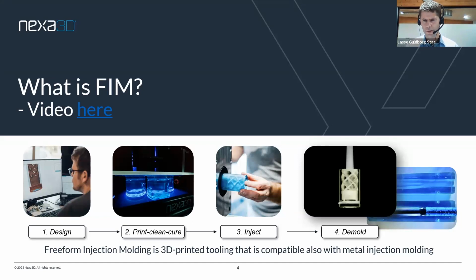Step number 3 is the injection of material into the printed mold. We use standard injection mold machines. We use standard injection moldable materials like the xMOLD feedstocks that Sebastian is going to talk about a little later. And then as the 4th step, we provide the injection molder with 2 alternative demolding patterns. For simple parts and for non-stick materials, we offer the opportunity of simply splitting tools apart like you would with a conventional tool. But for more complex designs and materials that may stick to the mold or may be fragile, like metal feedstocks, for instance, we offer the opportunity to dissolve a part. And the solubility of xMOLD is really one of the key enablers that allow us to manage very complex part designs with very simple tools.